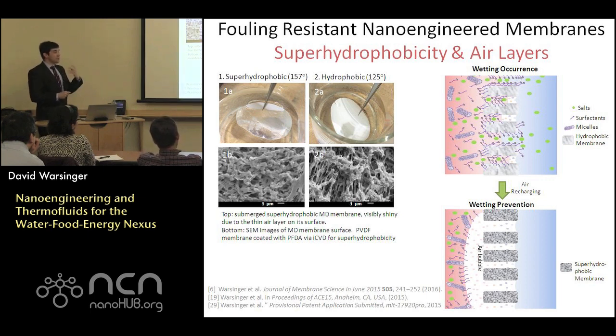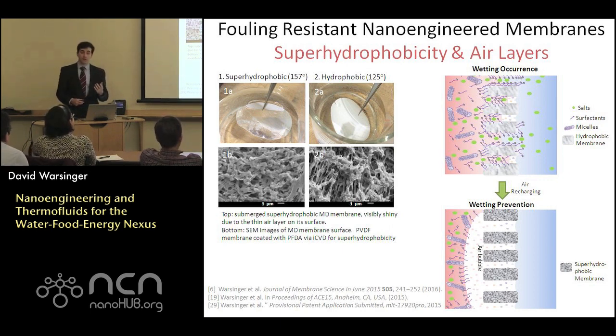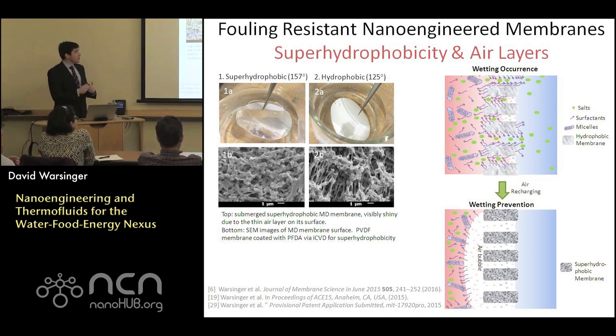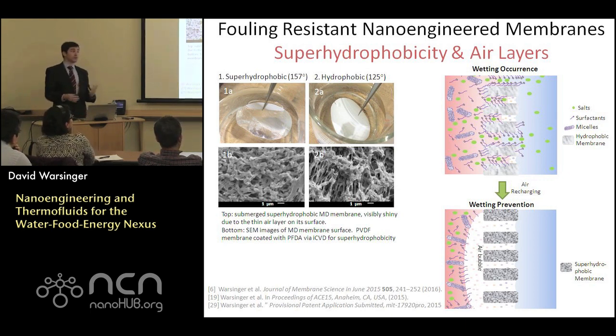I've looked at making hydrophobic membrane distillation membranes superhydrophobic. You can see a superhydrophobic membrane I developed versus the traditional uncoated version — at the SEM level they look very similar, so the coating isn't impairing overall performance. The permeability was almost the same between the two. When you submerge a membrane like this, you see a shiny layer on the surface — an effective air layer coating the membrane. Can we use superhydrophobic membranes and air layers to improve overall performance? If we have a superhydrophobic membrane, can we prevent membrane wetting, where hydrophobicity is lost due to foulants permeating through and reducing the contact angle below 90 degrees?